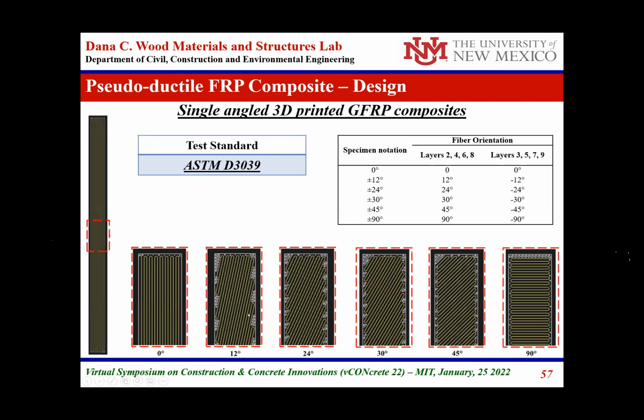Going from the orientation of the FRP here going from 0 orientation to 90 degrees, by changing the number of layers at each one of these and the angle of orientation, we can control the stiffness of the material. And with the control of the stiffness, we can achieve the concept of the shared stiffness we have been discussing earlier.